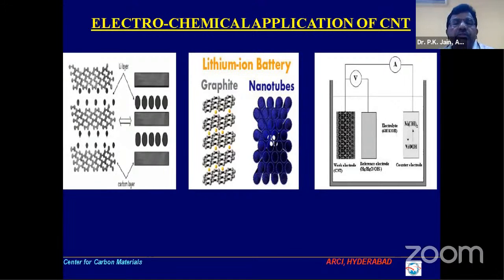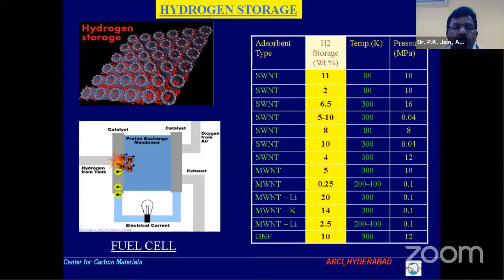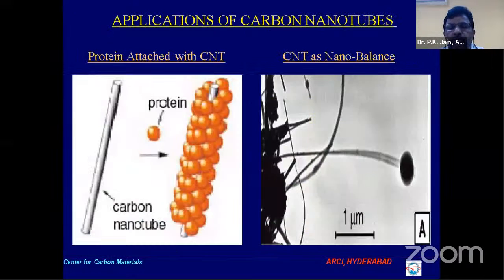Now another application is electrochemical applications of CNTs, whether it's in lithium ion batteries or something, where the ion goes into the host, such as graphite. In hydrogen storage, this was very popular once upon a time, but there are a lot of controversial reports because the consistency of the results was not there, sometimes 2%, 11%, 4%. So many people are not working on it, but if you do systematic research, this is still one of the possible candidates for absorbing hydrogen. Carbon nanotubes can also become a substrate for protein absorbing, or act as a nano balance because they hold the material very strongly.